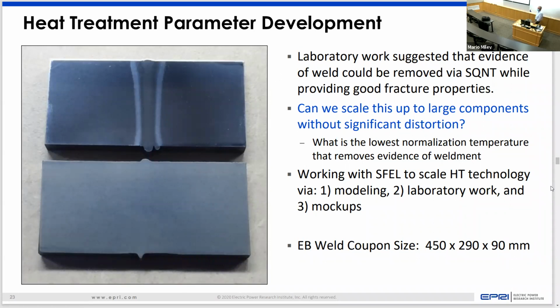Many of the early reactors that were built in the US used what I would say were somewhat inferior filler materials in terms of they had tramp elements like phosphor and sulfur and copper, which ultimately led to embrittlement of some of those. We have to watch those very closely. We know where those are at and we know what the life of those are. What we're trying to do here, though, is because you're not putting any filler material in with the electron beam process, you go through a heat treatment situation where you can actually essentially remove that weld.